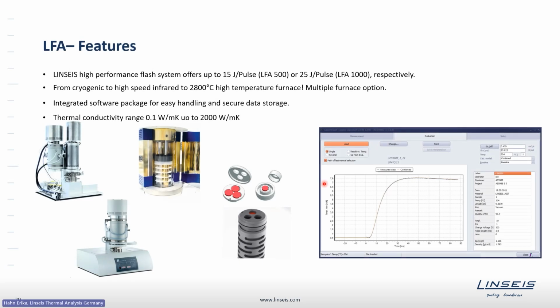Basically summarizing the laser flash features, the Linseis laser flash is a high performance tool, available either with a xenon lamp or a laser, offering different analysis tools. We have different furnaces from cryogenic temperatures up to 2800 degrees Celsius with a high temperature furnace, where you see here an example of that.